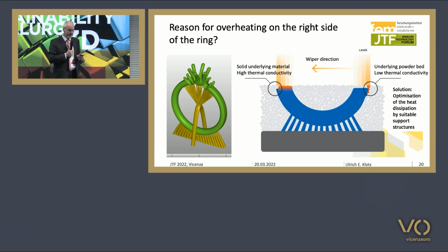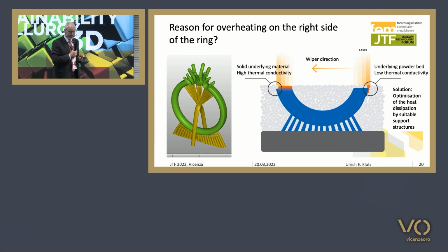So why is this happening? This is our 3D model of the ring with the structures, and on the right side we see a sketch. We applied the powder from the left with a wiper, and we also start lasering from the left. On the left side when we start lasering, due to the geometry, there is solid material below, so the energy can be dissipated into the ring shank, while on the right side, in the very beginning of the laser process, there is a powder bed below this region. So the energy cannot be dissipated, and therefore we get this overheating.